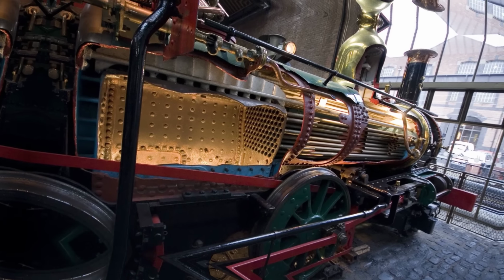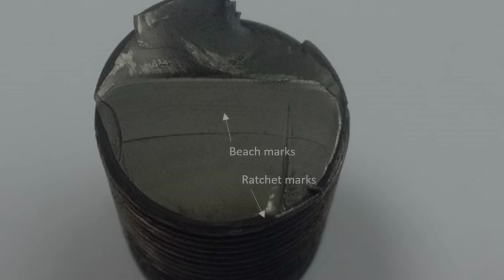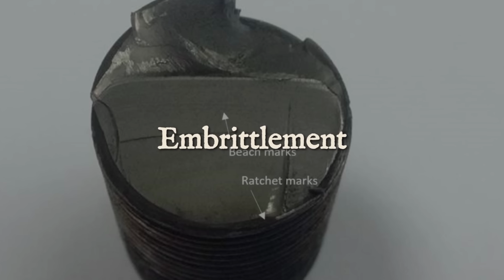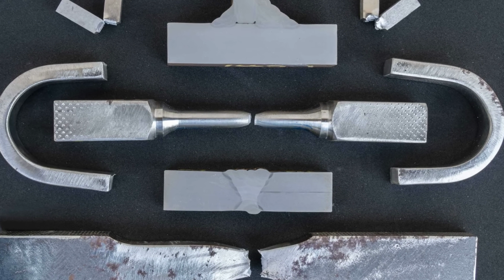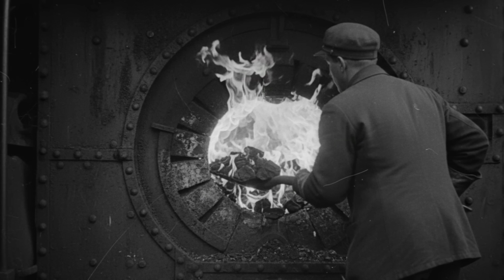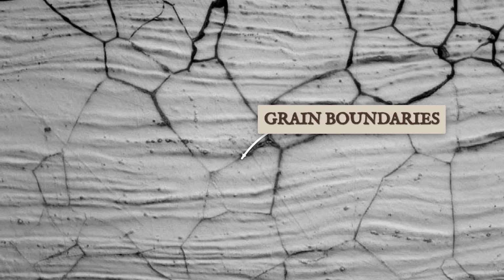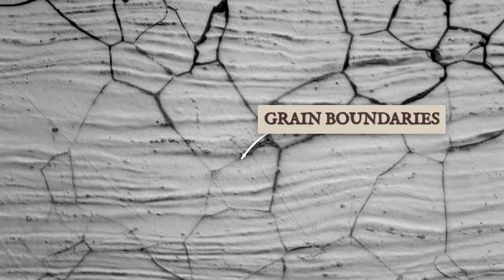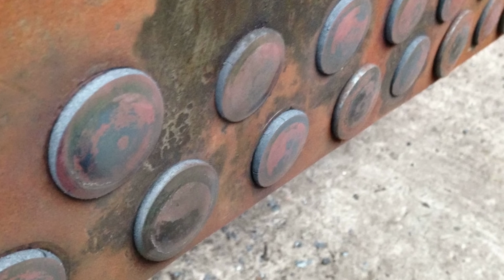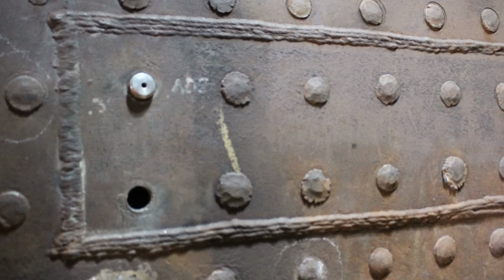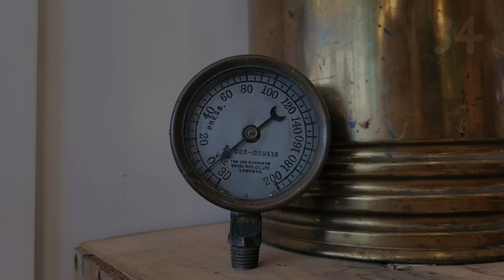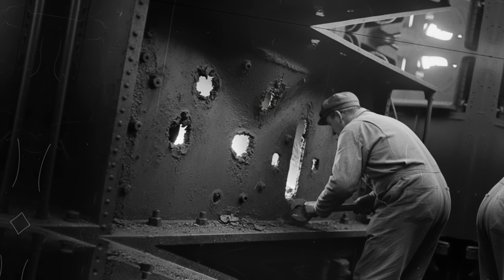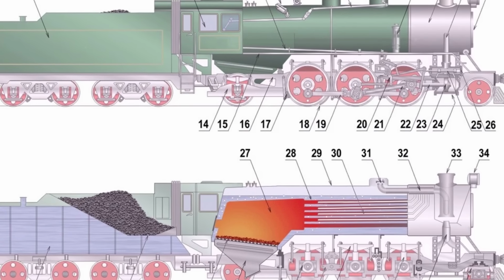Superheater elements, exposed to the hottest gases, face a different enemy: embrittlement. At sustained high temperatures, steel loses its ductility. Oxygen and sulfur in the firebox atmosphere attack the grain boundaries, turning tough metal brittle. A stay bolt or tube that might bend under pressure now fractures cleanly. The margin for error shrinks with every degree above design specification. When enough stays fail, the crown sheet is no longer a barrier, it is a trapdoor.